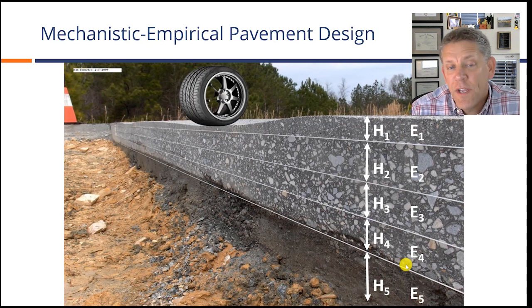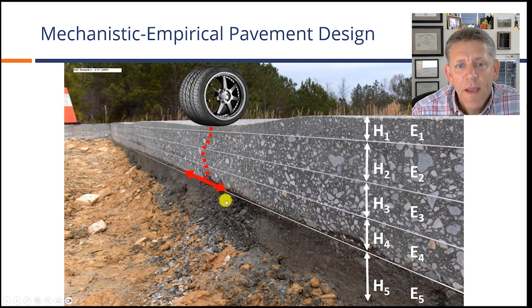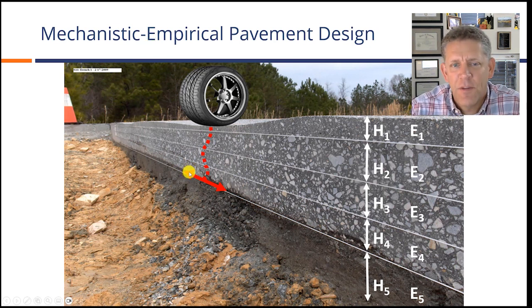We then simulate a loading event on the pavement surface and use a mechanistic model. So this is the M part of ME design. We use a mechanistic model to calculate a critical pavement response. And then we have an empirical relationship that links the mechanistic response to an empirical prediction of performance. So we know we have a certain amount of strain happening in the pavement under this set of conditions, and then the prediction is made empirically about how much cracking we're going to see. We can do that for bottom-up cracking. We can also do that by looking deeper in the structure at the pavement responses there and make a prediction about how much rutting we might see. And so that's the two parts.